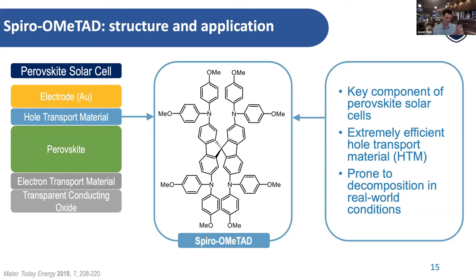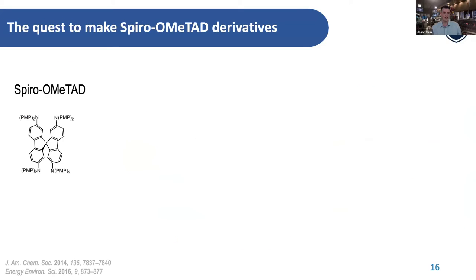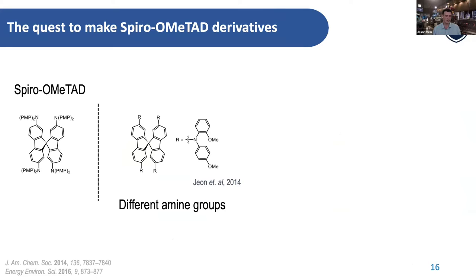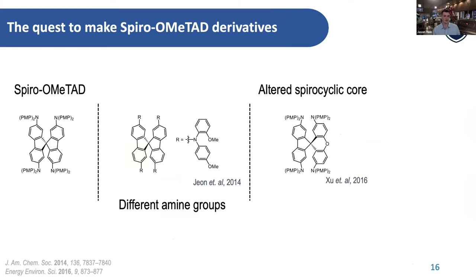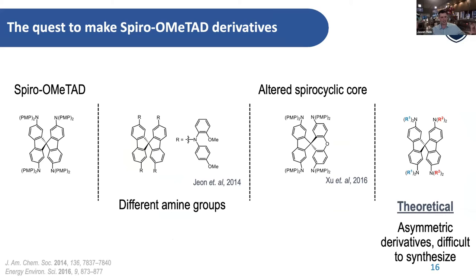Not only that, understanding how to build this type of molecule in terms of its mechanism allows us to change that core molecule and tune its properties. So synthesizing this becomes a key challenge, doing it well. What's interesting about the synthesis is, it's just this very simple spirocyclic fluorene core with this electron-rich periphery of polyaryl amines. We'd want to be able to decorate and change these groups to other substitution patterns or other electronics. And these altered spiro cores each have a different flavor in the materials community. They have different physical properties and conductive properties. So being able to come up with a very clean route to systematically address these positions was really the key barrier here.